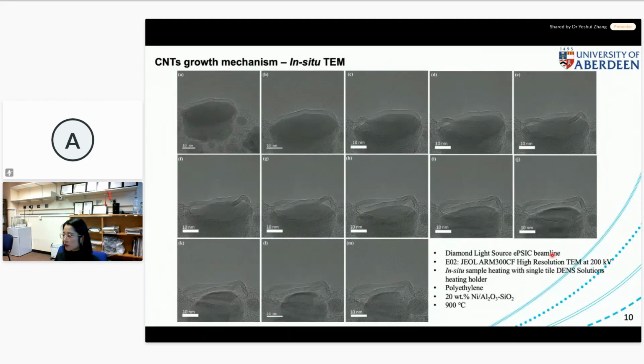And regarding the latest research on the CNT growth mechanism, as I mentioned, this is one of the biggest challenges. I have discussed this in my review article. So we have to use the most advanced in situ instruments, or alternatively, we can develop in situ metrology to help us understand the mechanism. Why? Because this is a dynamic process. The formation of these carbon nanotubes on the catalyst surface can happen almost immediately, as long as the carbon atoms released from the plastics reach the catalyst support. If you look at these TEM images, they were captured using in situ TEM earlier this year at the Diamond Light Source, which is a synchrotron source based facility.